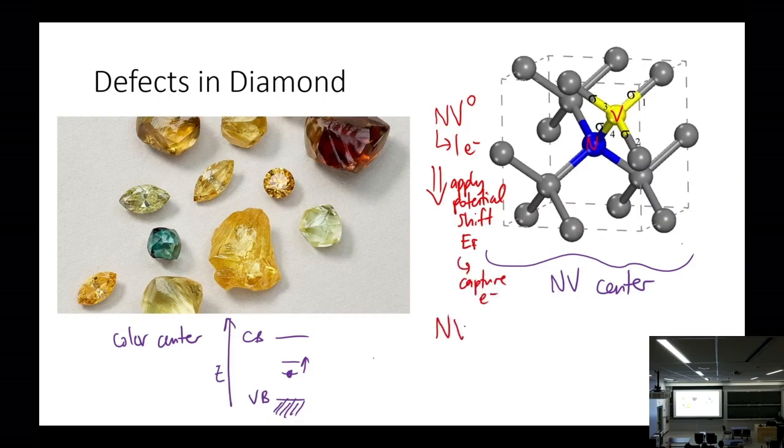And that's what makes the very special NV- center, which is an S equals 1, 2 unpaired electrons, ground state. And it has the exact same kind of fun situation that I just laid out in the vanadium example. So it has little m sub s equals 0 ground state, and it has a pair of little m sub s equals plus minus 1 excited states.